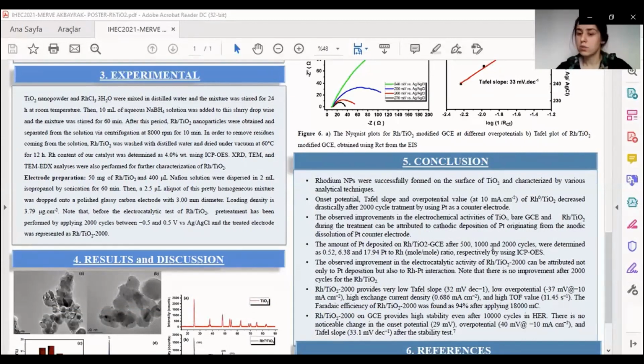500, 1000 and 2000 cycles were determined as 0.52, 6.38 and 17.94 platinum to rhodium mole ratio, respectively, by using ICP-OES spectroscopy. The observed improvement in the electrocatalytic activity of rhodium titania 2000 can be attributed to not only the platinum deposition but also the rhodium platinum interaction. Note that there is no improvement after 2000 cycles for the rhodium titania.